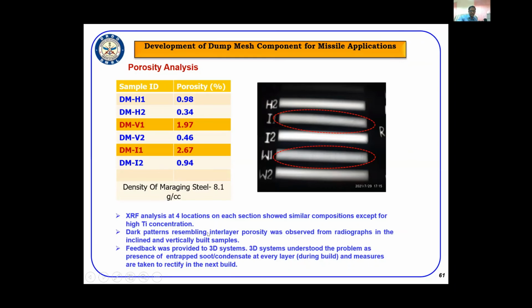And dark patterns, again, interlayer porosity, were observed from radiographs in the inclined and vertical build samples. So this is again the inclined and vertical build samples, where we could see these dark patterns. That feedback was given to 3D Systems, and after a discussion we could understand that the problem is related to entrapped soot or condensate. That means when the 3D printing or deposition of the component is made, a lot of soot is generated, which, before the next layer is deposited, will form onto that layer and result in some sort of impurities. Then we have taken necessary measures to reduce that and to rectify it in the next build.